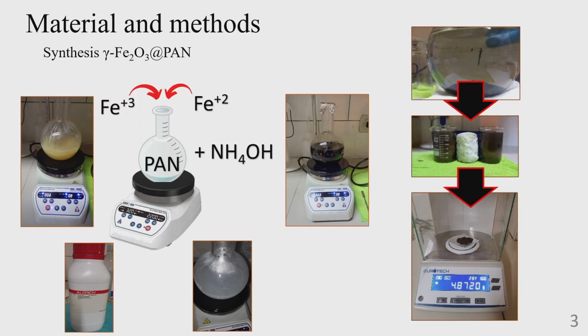During agitation, small lumps form that were dispersed with an increase in the revolution of agitation. Then the iron salts are added, maintaining the agitation and temperature. After 10 minutes of stirring, another 25 milliliters of ammonium hydroxide, concentrated at 33% by volume, is added. It is here that the first evidence of the magnetization of the sample is observed when approaching a neodymium magnet.